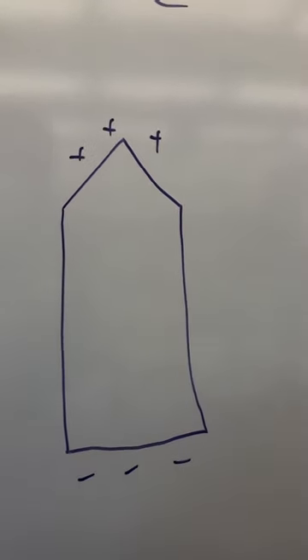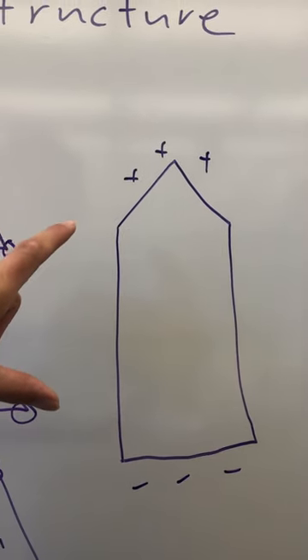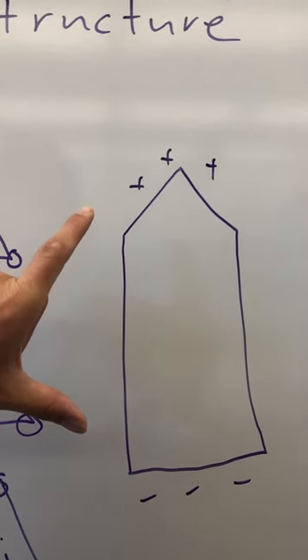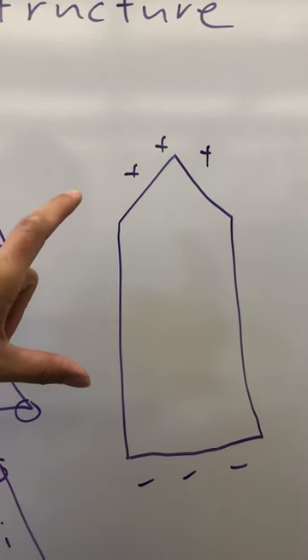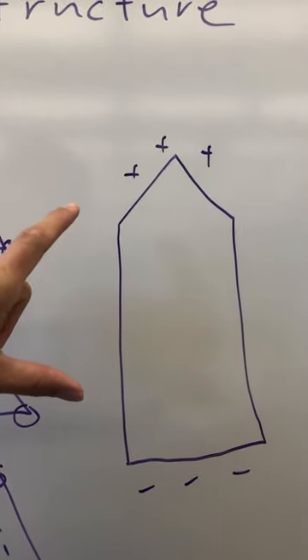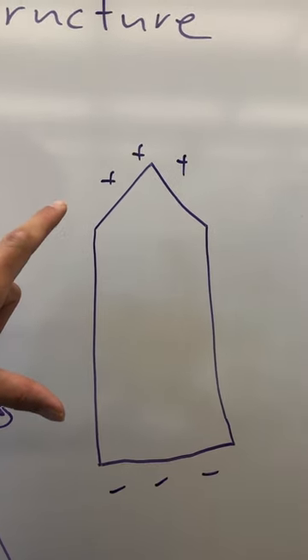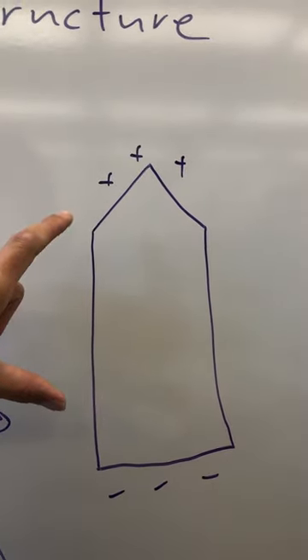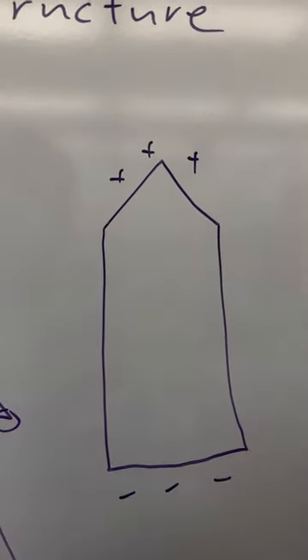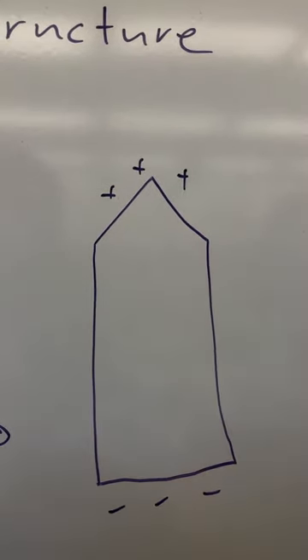Now, one way to get that is to literally squeeze the crystal. We can also, for tourmaline at least, we're getting electricity by squeezing - that's called piezoelectricity. In tourmaline we can also get this effect by heating or cooling it, because thermal contraction in tourmaline is slightly asymmetric, and it contracts more lengthwise versus crosswise. And so that squeezing from the cooling will give it the same effect.